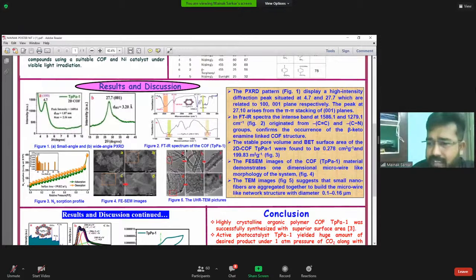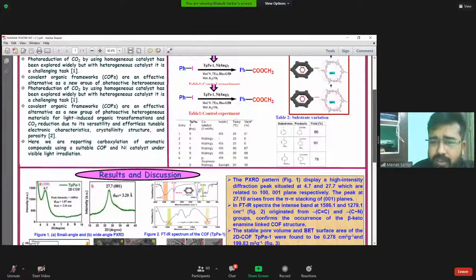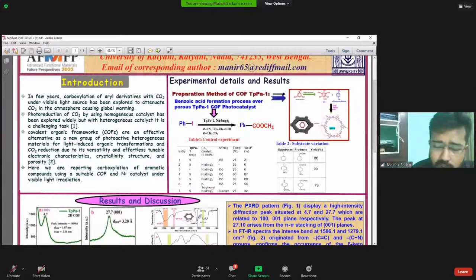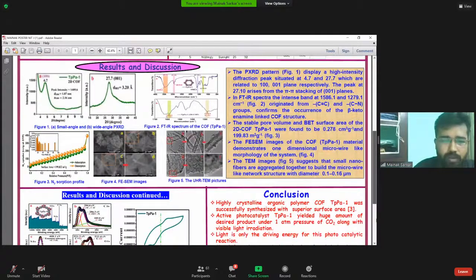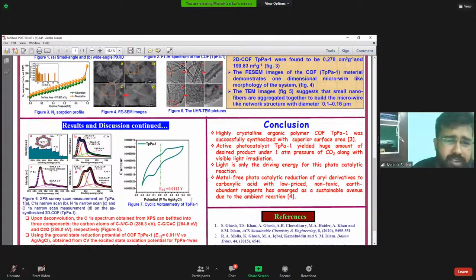We have applied this in the carboxylation of aryl derivatives. We have used iodobenzene as the basic form, and different substrate scope has been done. With any electron withdrawing group, it shows definitely higher yield, and with any electron donating group, it shows relatively lower yield. Okay, sir. That's all. We have also done cyclic voltammetry and XPS analysis for characterizing this material.